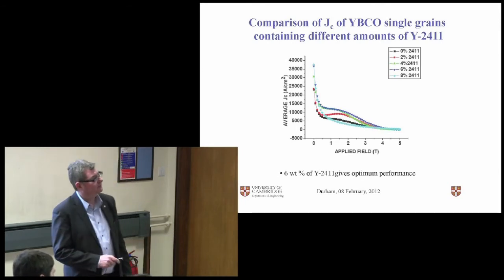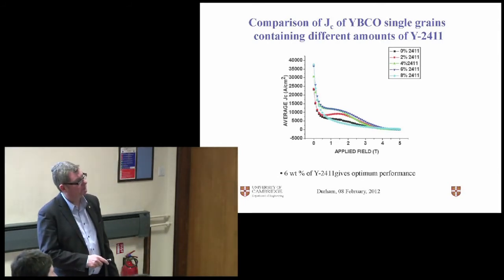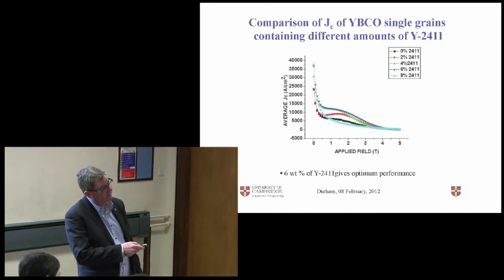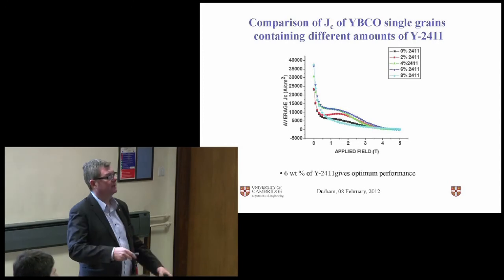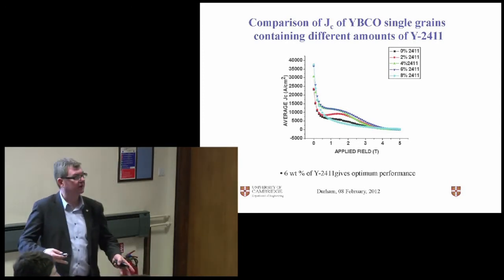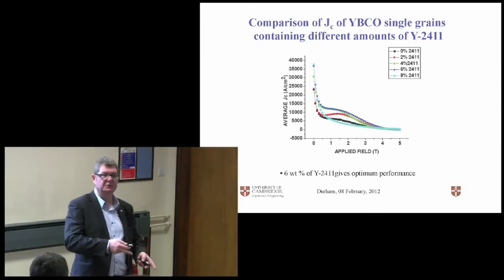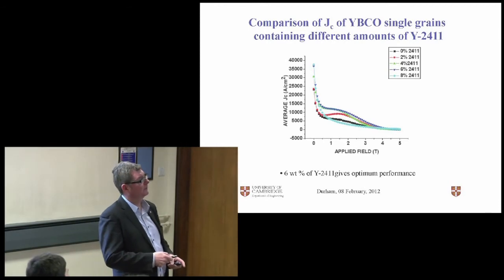And we can just compare Jc. Remember, we want Jc to be as big as possible. That gives us the biggest possible fields. And if you systematically add more and more 2411, eventually you get too much of a volume fraction, so you don't have the superconducting cross-section to carry the current.